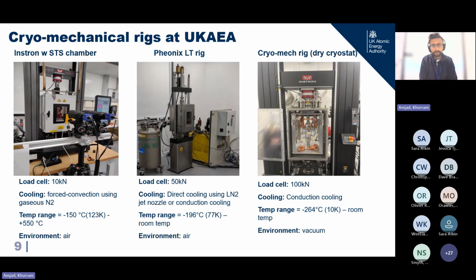We have got a Phoenix LT rig, which is, I believe, managed or maintained by Darvick. It has a 50 kilonewton load cell. It can do direct cooling, so direct injection of LN2 through nozzles. That has the potential to reach up to 77 Kelvin, and the environment is air. It's not a vacuum chamber. And it has a window as well, so we could potentially do DIC on it, but we haven't really explored that at this stage.